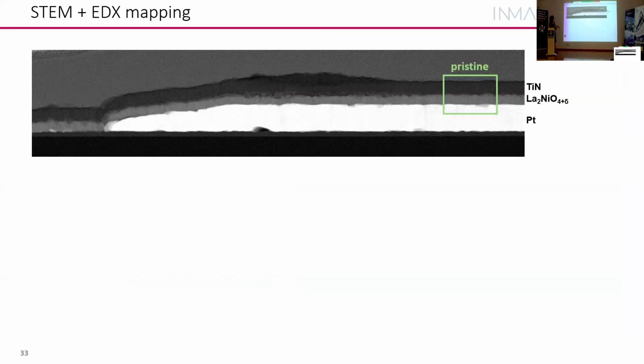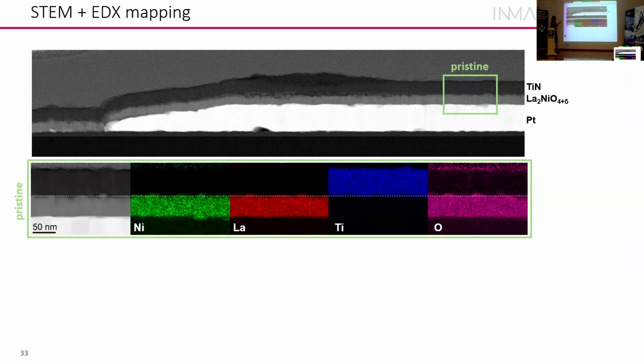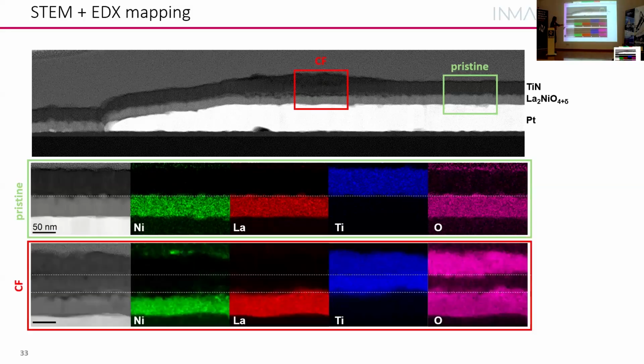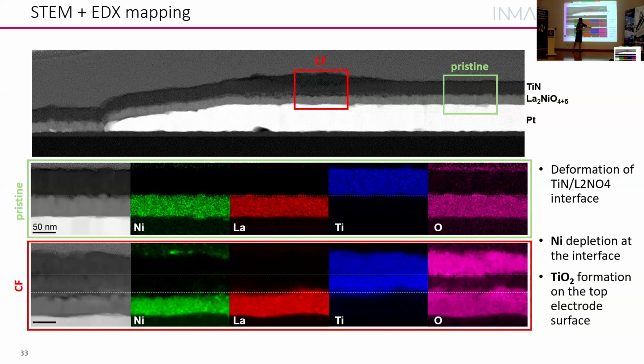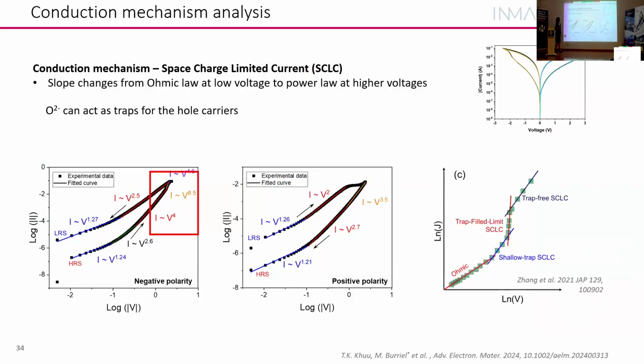And here is what we see. That is the pristine region. Each element is where it should be. Nothing has moved in this region. But now what happens if we compare with the conductive filament region, which is this part here? Here we can see changes, a nickel depletion. Nickel is not here anymore in this top part of the nickelate where it was before. And here we can find some titanium oxide formation at the top of the electrode surface.